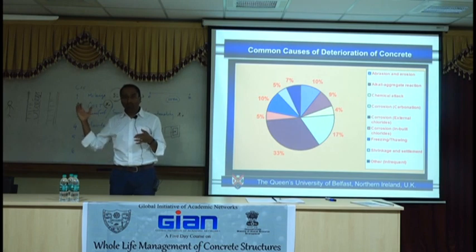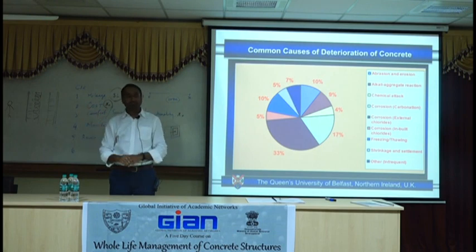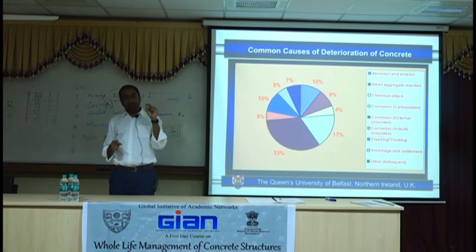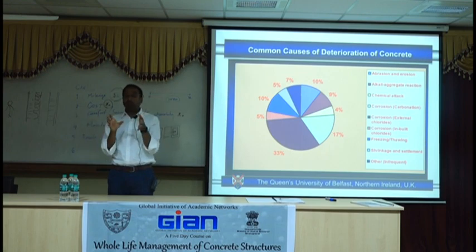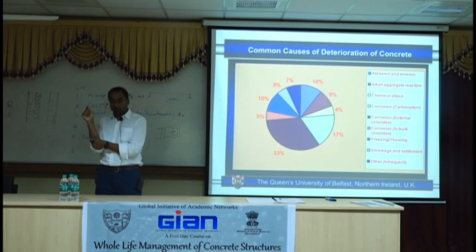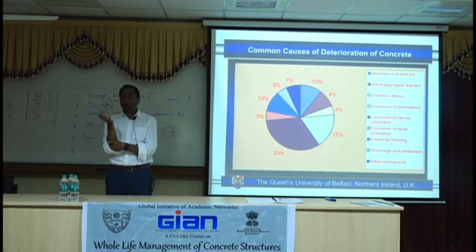And then a few hours later, our fantastic weather, rain comes in, takes away all the salt, puts it very nicely on the structure, and then the roads are clean. But the water is there, which means the water will freeze over. So the second round of lorry has to come in the night. This can happen 2-3 times in the night, every night. Even when you microscopically look at a couple of hours in the night, our temperature is not too far below zero, but it doesn't really go into the negatives, which means we just keep going up and down all the time. That's really bad. In terms of freeze-thaw, we have many more cycles in a day than some of the coldest parts of the world.